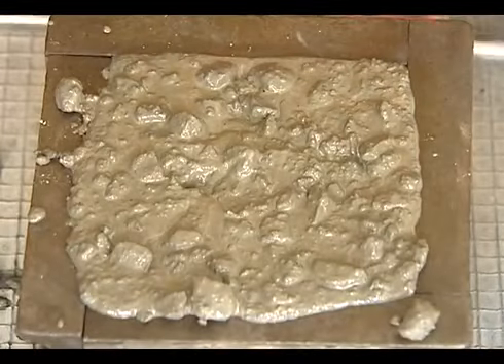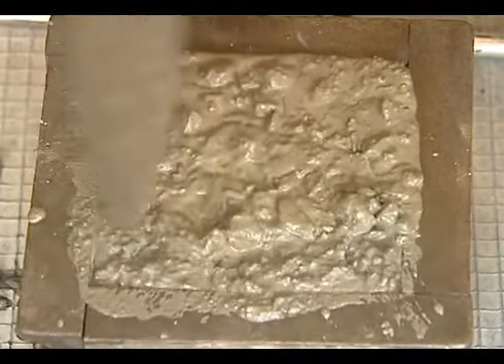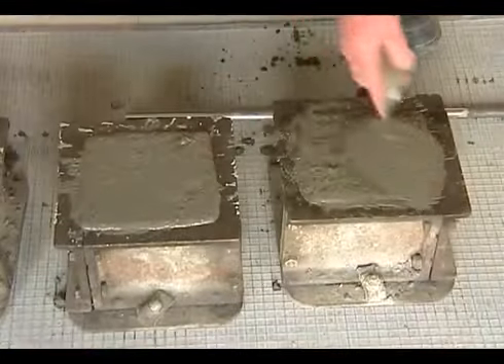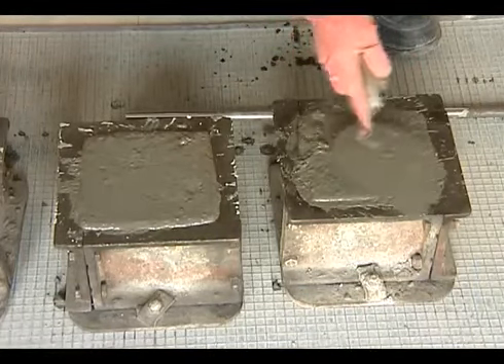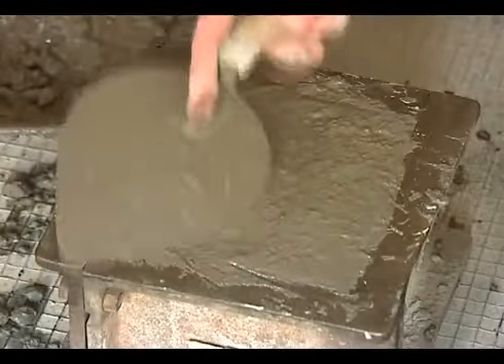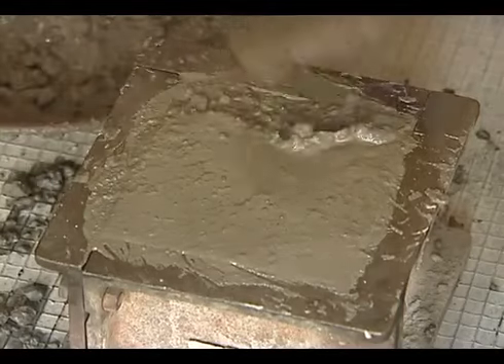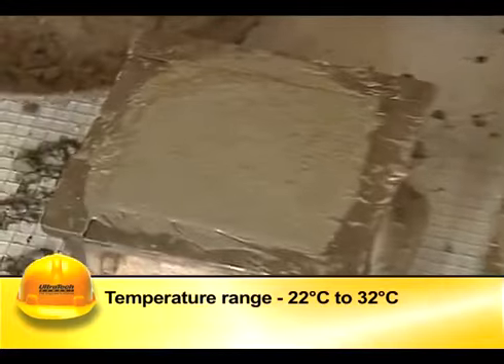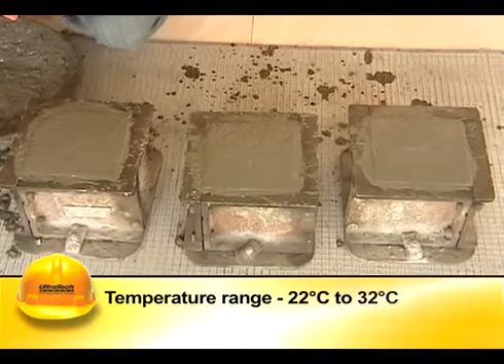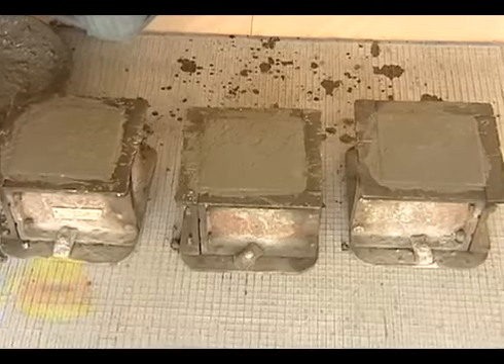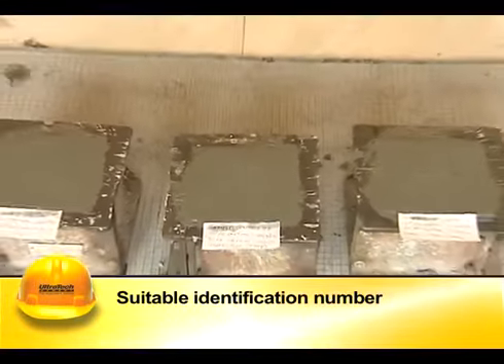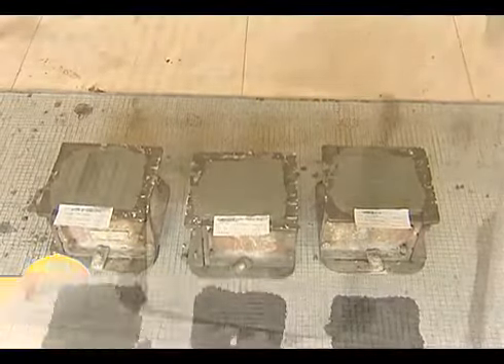After compacting the top layer, the surface is made flush with the edges of the mold using a trowel. The mold is covered immediately with damp Hessian cloth and left undisturbed for 24 hours. Site specimens should be stored at 22 degrees Celsius to 32 degrees Celsius. The cubes should be marked with a suitable identification number when slightly hardened to facilitate easy identification at different ages.